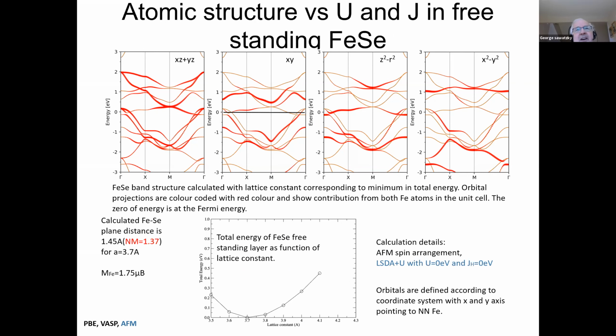And the reason is that if you have a local moment, you cannot have 2 electrons in every k state. This means that these anti-bonding iron D states, relative to the selenium, you have to occupy more and more anti-bonding, higher energy states. And as soon as you occupy higher energy anti-bonding states, the bond itself is becoming weaker, and the distances are going to become larger. And this is exactly what happens. We've done this study for the iron oxides, for iron halides, and every time, if you look at a low spin, high spin transition, you get the same kind of thing again, for example, in lanthanum cobaltate. So whether you have a local moment matters much more than how it is actually ordered. And that's what I want to show you.